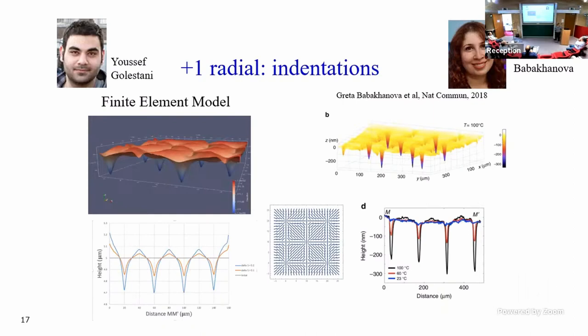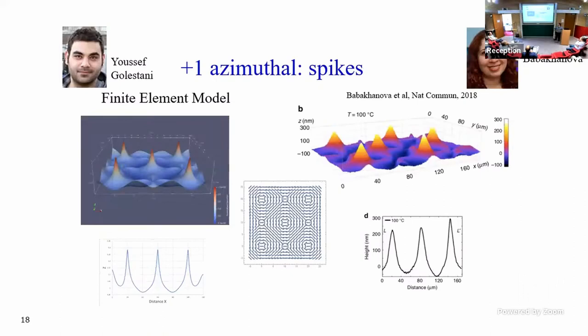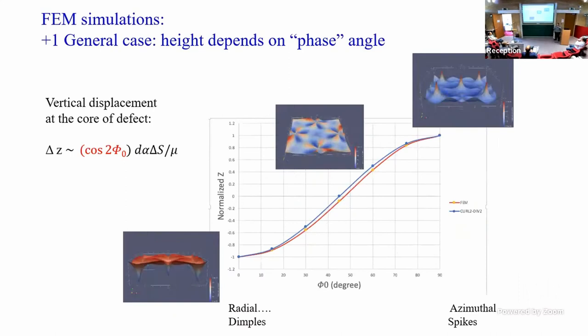On the other hand, if you change the orientation of the defect so they're azimuthal instead of radial, just like making those cones, these things pop up and you get little emerging, I don't know, they're not exactly volcanoes, but little pointy things coming up, and you can see the simulation more or less exactly matches the experiment. And then we tried changing the angle continuously between radial and azimuthal, and you can see that the displacement out of the plane just follows a simple cosine two theta function. Jonathan has some theory to explain that, but I don't have that in this talk.